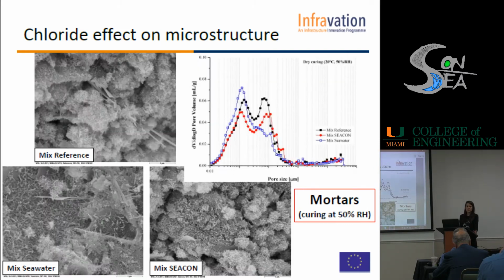Then we produced the same mortars and we stored them in dry conditions at 50% of relative humidity to see what happened. And from the pictures you can see that the mixed reference has also in this case a better structure. So the hydrated phases are recognizable also in these cases, but the structures are different from the other one. So we performed MIP also in this case, and we can show that mixed reference and mixed SEACON have a bimodal distribution. They have two different families of pores in this case.